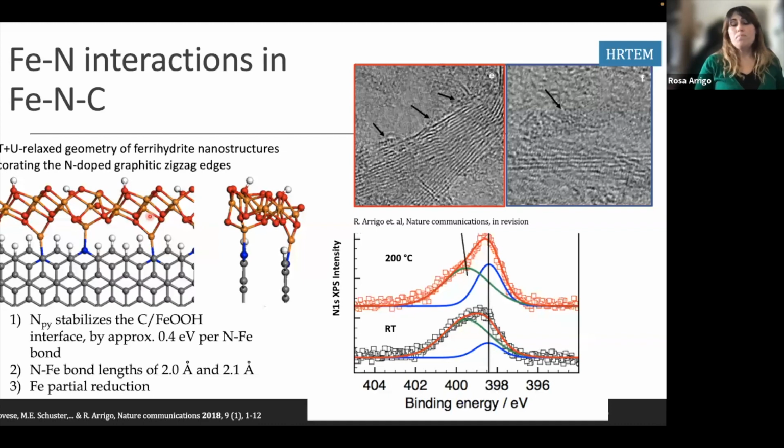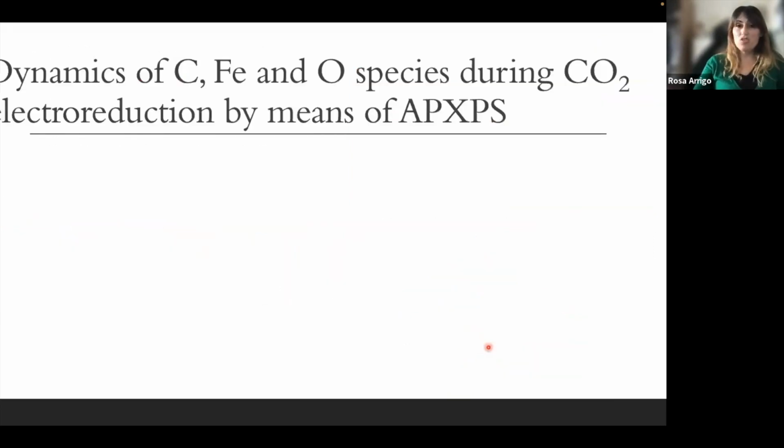species. And here, by doing XPS, I show you, as I said before, that of course looking at N1s and the iron metal coordination is very difficult because the peak is broad and it overlaps with other species. But what we show here is, for example, that when we anneal these materials, the pyridinic nitrogen's intensity increases, and this shows that part of it was previously coordinated to iron, and by annealing we have freed it from the iron species. So to a certain extent we could confirm the coordination.